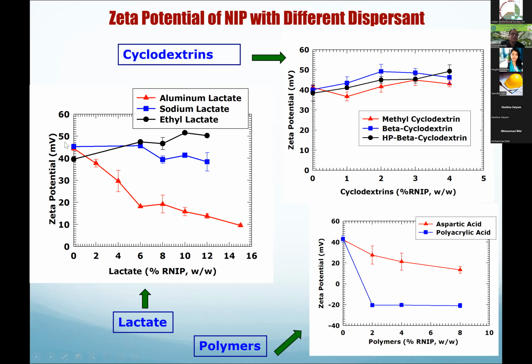So we are looking at the zeta potential. You have a positive charge. And if I use this ethyl lactate, you see the surfaces are becoming even more positive. And sodium lactate, if I use it, it's kind of the same and slightly decreasing. Whereas if I use the aluminum lactate, you see that it is decreasing significantly. So the surface charge of the nanoparticles would be decreasing.